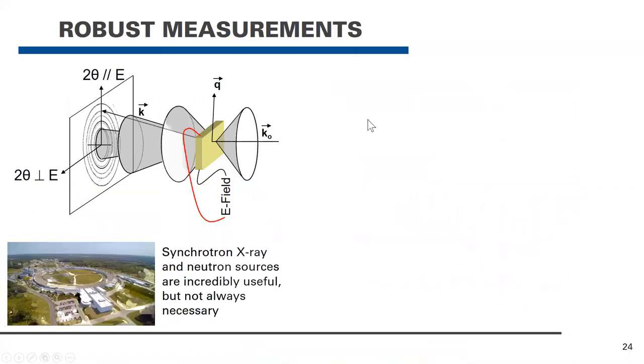So nowadays we do what I would say are more robust measurements, and many groups across the world do these types of robust measurements. So typically we use a high energy X-ray source produced from a synchrotron. We'll put our sample in the synchrotron beam. The high energies allow the collapse of these cones to very small angles. And on a two-dimensional detector, you can capture the Debye-Scherrer rings. Now, the important thing to note here is that in the vertical direction of the detector, you have information from scattering that represents scattering vectors approximately parallel to the electric field direction. And perpendicular, you have information in the scattering pattern from scattering vectors that are approximately perpendicular to the electric field.